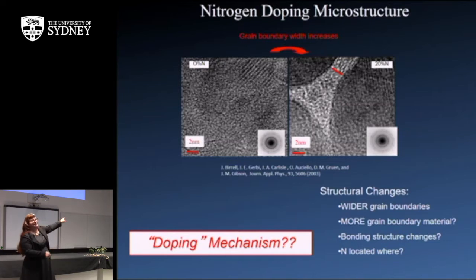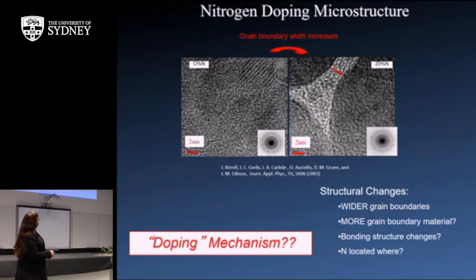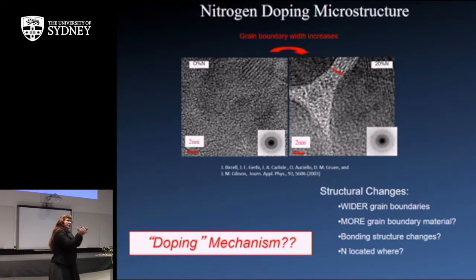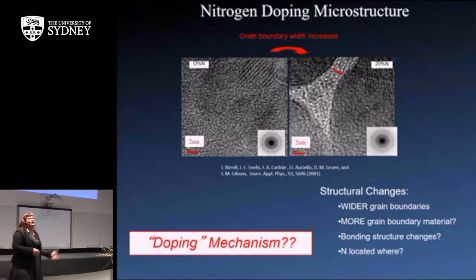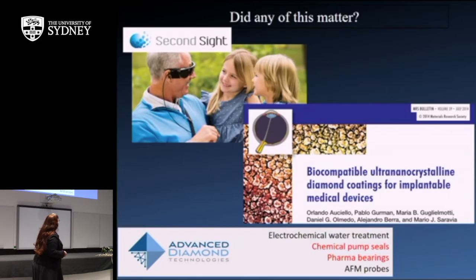And I took these pictures. It's sort of hard to get these pictures at the time, so I'm very proud of them. But again, this is 2 nanometers. You can't even really see where the grain boundaries are. When you grow with nitrogen, you actually get these slightly wider grain boundaries. And what you have happening here is that electric conduction is going through the grain boundaries and not the grains themselves. But the bulk of the film is still made up of these little single crystals of diamond, so you still have a lot of diamond characteristics in the film. So it ends up being very useful.